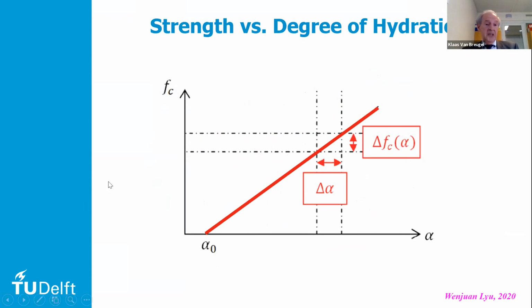If not, in the end, the sample will fail when you have a very high load level, then you may have this progressive collapse as we have seen in the previous one. But at a moderate load level, this might then happen, that you have an increase in strength.